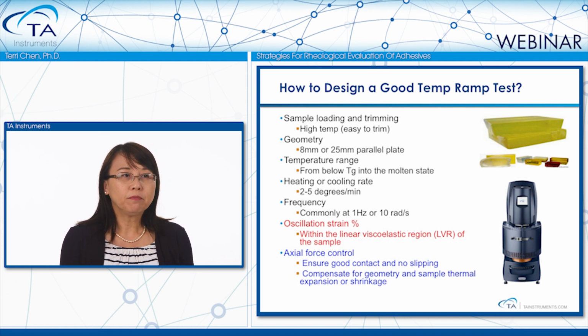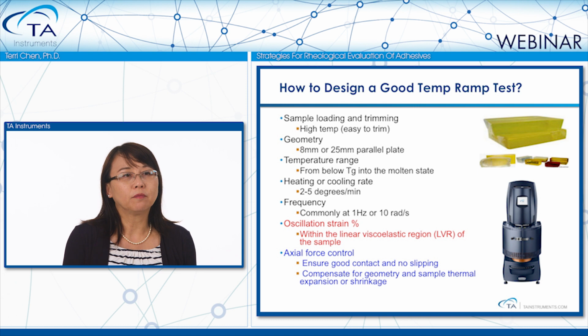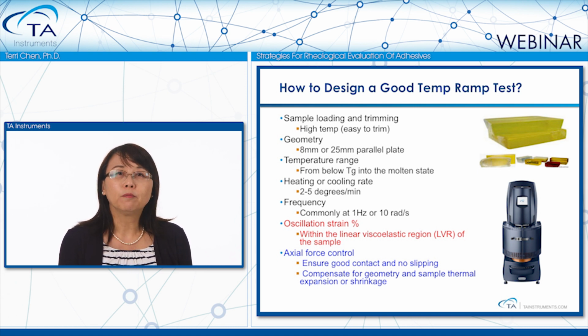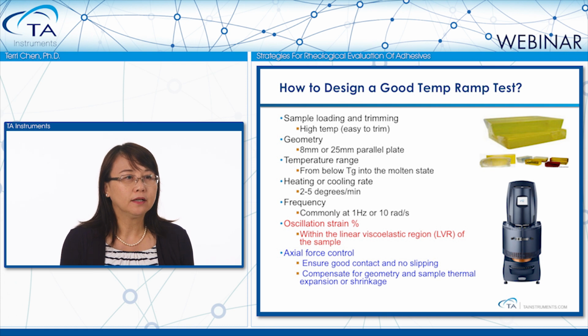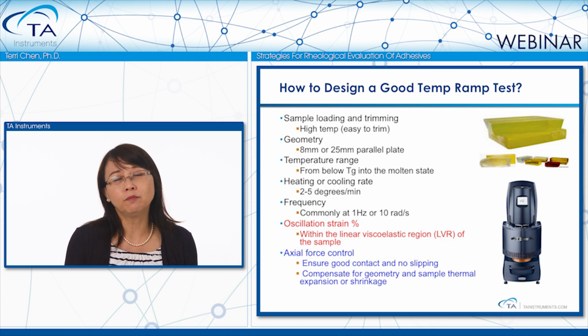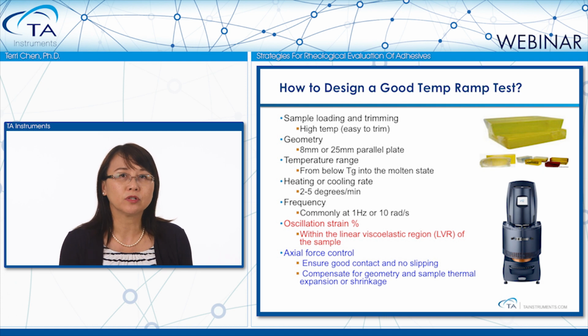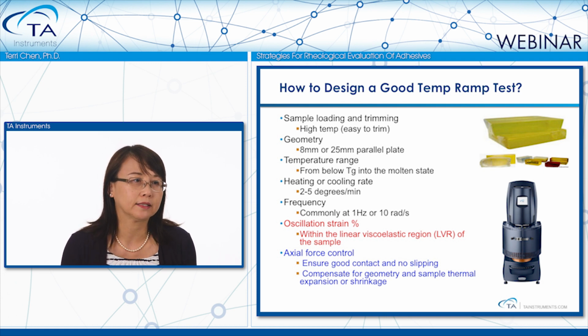The measurement temperature usually goes from below the glass transition until the sample is molten or before it degrades. The commonly used heating rate is 2 to 5 degrees per minute, and the commonly used frequency is 1 Hz, or some people use 10 radians per second.